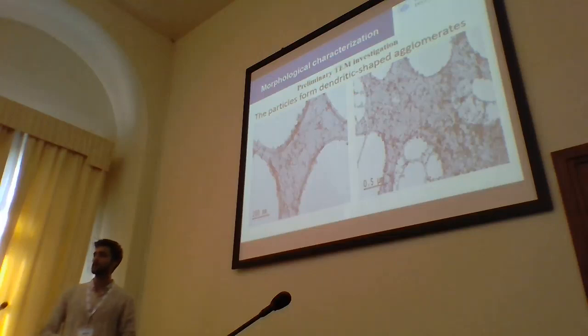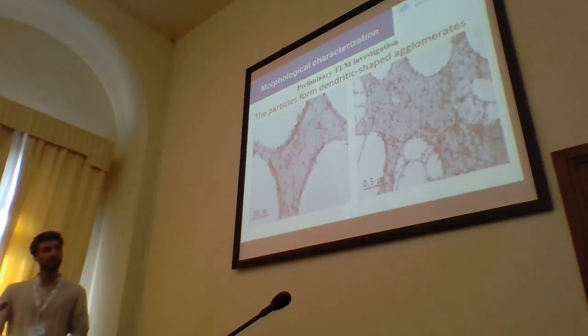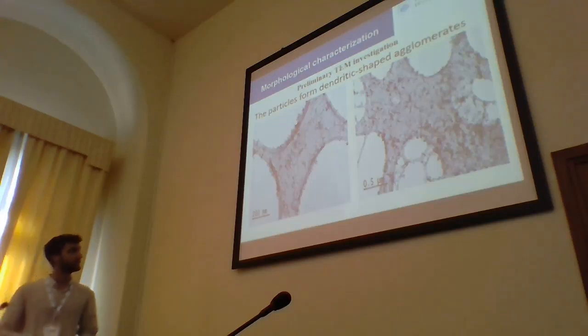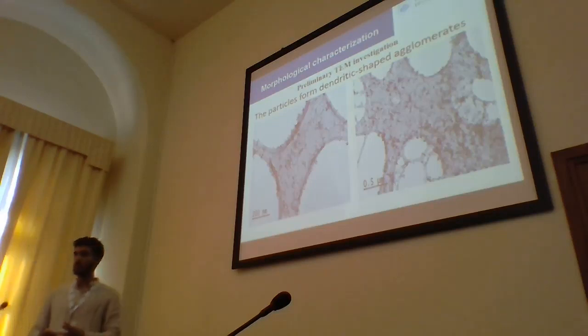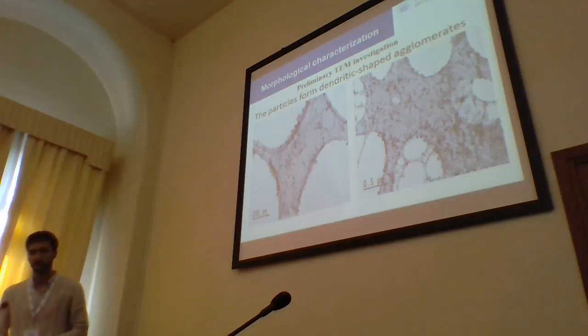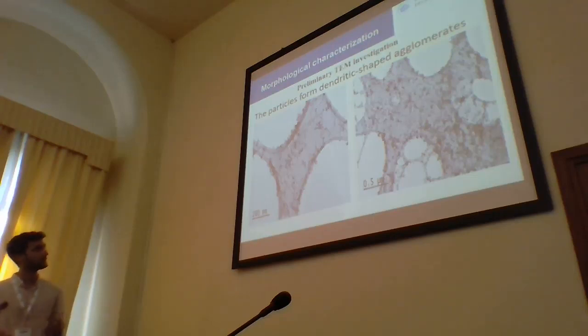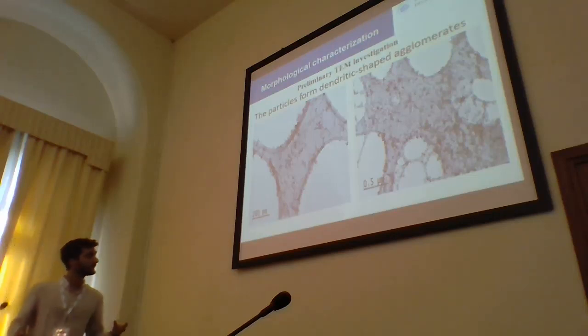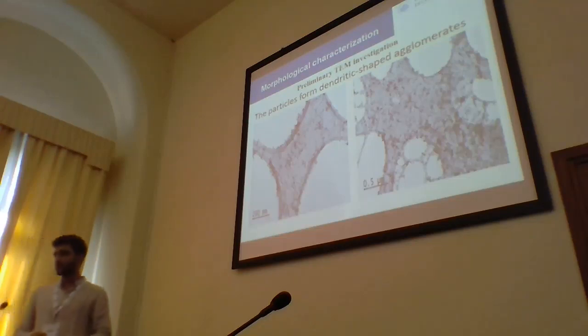But electronic structure is not everything. It's also important the crystal structure and the morphology of the nanoparticle. These are important parameters when we talk about nanoparticles. This is a TEM image with a low magnification. You can see that the nanoparticles I produced assemble in these dendritic-shaped agglomerates.